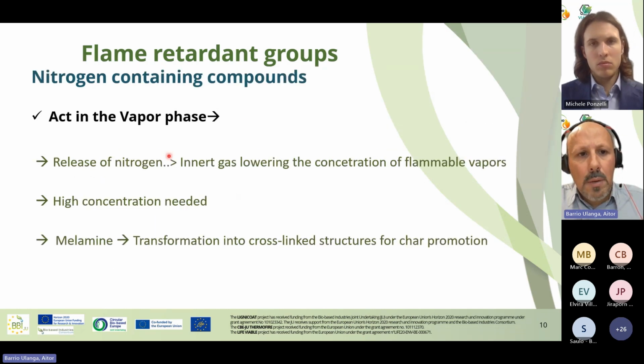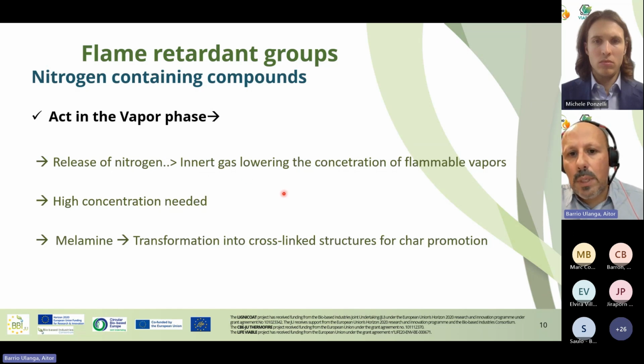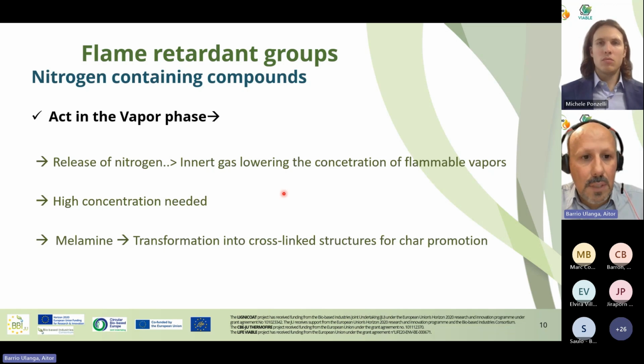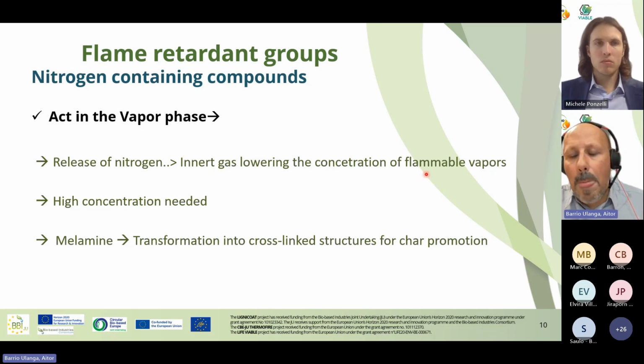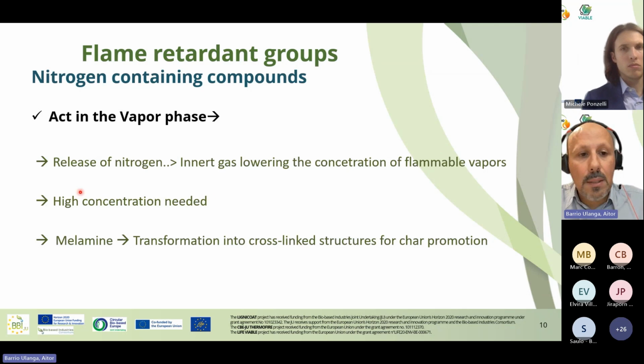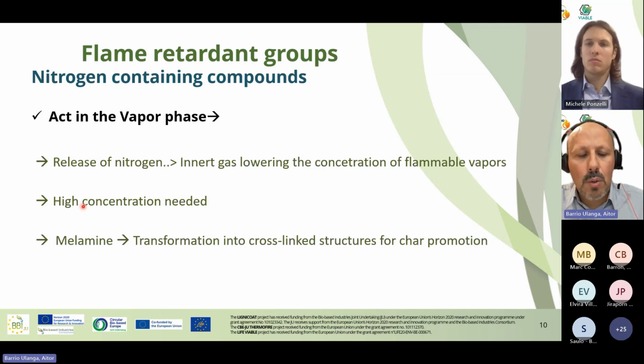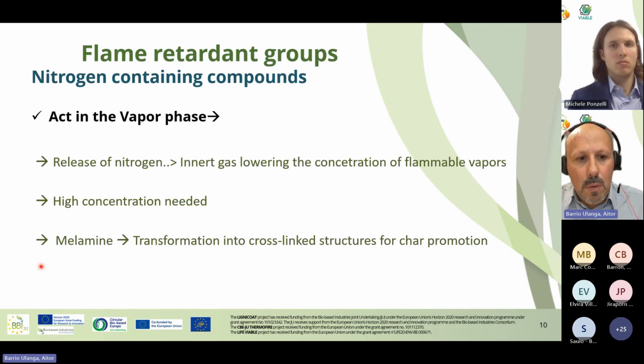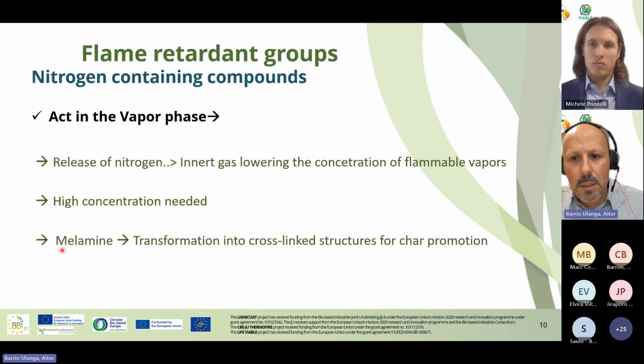Nitrogen-containing compounds: the mechanism is to release nitrogen. They have nitrogen in the structure, so with the heat, they release an inert gas, nitrogen, and dilute the concentration of the flammable substance in the gas phase. So it is another mechanism, but this is not so effective, so you need a high concentration of this material. One of the most famous is melamine, which also promotes char formation.